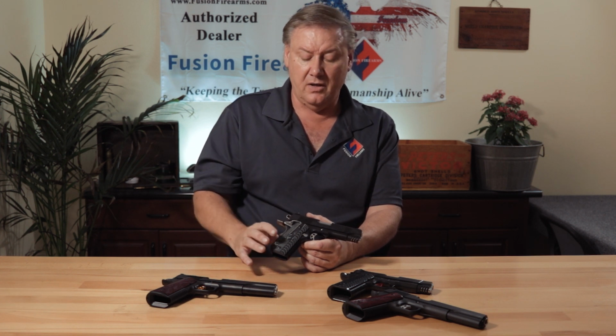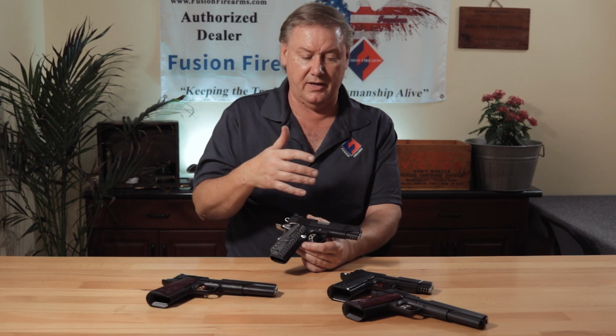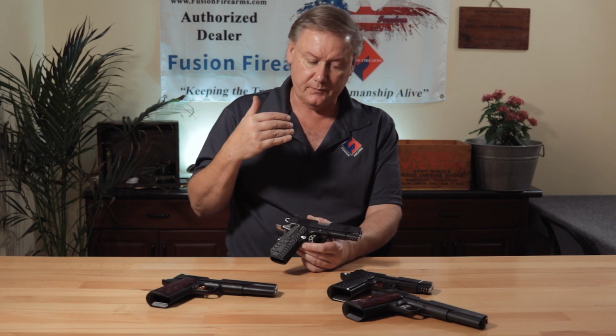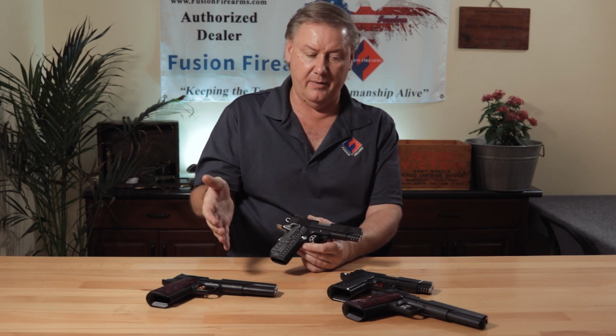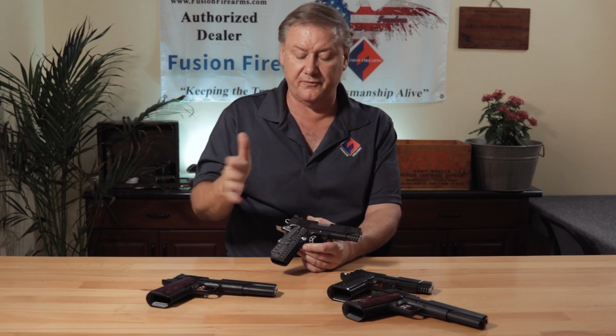It will still penetrate, carburize the surface, and give you a beautiful, consistent black finish. And same with the Ion Bond. You can put Ion Bond over top of pretty much anything also. The only thing that you'll have issues with, with any of the finishes other than the paint, would be the hard chrome. If you try to go over the hard chrome with Ion Bond or black oxide, even if it's a carbon gun that's been hard chromed, or try to put the Nitro Carburizing on a hard chrome gun, it generally will not work. You need to strip that finish off, and certain finishes, yeah, you can take it to your sandblaster, bead blast it off, and you're good to go.